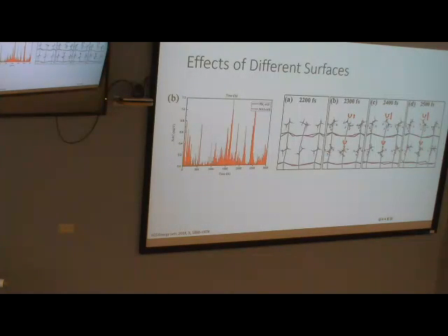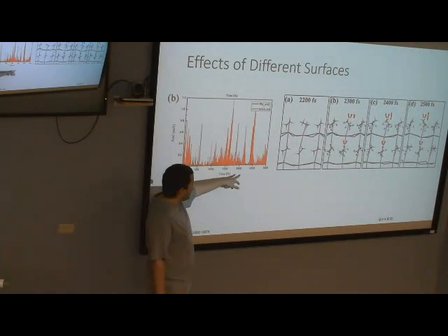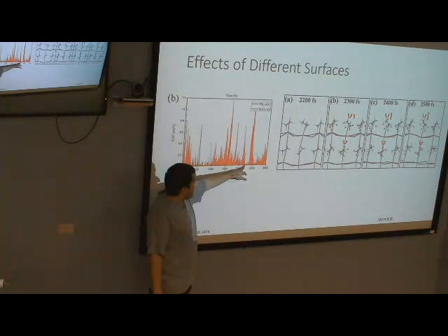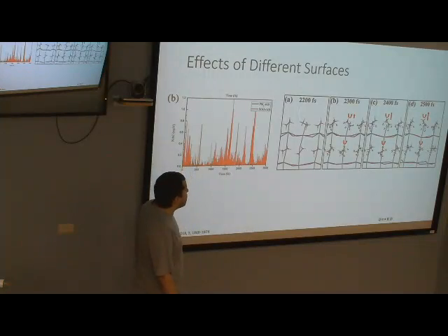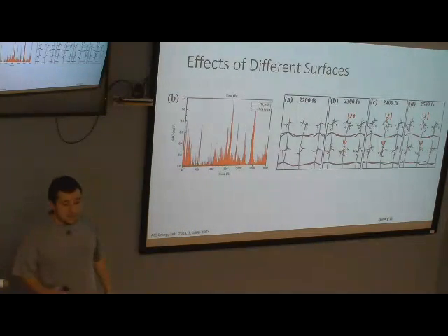So right here is a graph of the non-adiabatic coupling within time. So what they did right here, they took screenshots of the range of 2200 to 2500, because that's when the non-adiabatic coupling was found out to be at its highest peak. This is due to the methyl ammonium cations rotating within the cage and increasing, making it bigger, the lattice that's inside it.